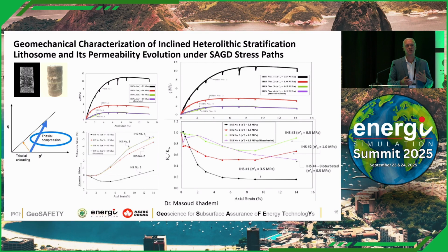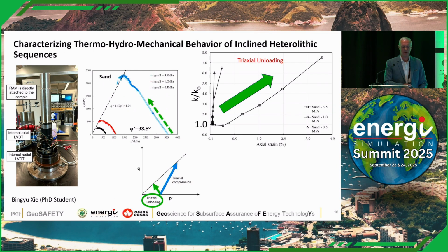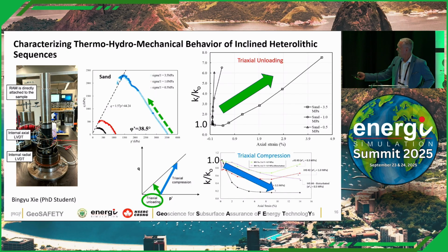What about heterogeneity in the samples? This one has small layers in it. All of this stuff, we did this. So this is triaxial compression again as a stress path. And if I switch this around, now this is the start of the argument, to triaxial unloading. I go to the left under injection. The permeability goes up, but in triaxial compression, the permeability went down. So if you're under an injection stress path, the permeability will almost increase instantaneously, as opposed to using a model where you got permeability change from a triaxial compression test.